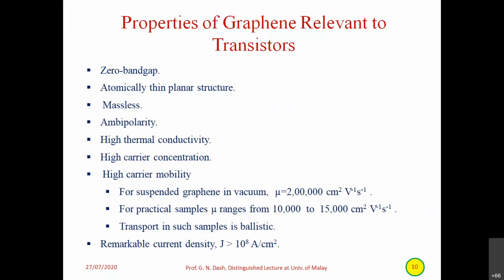For suspended graphene, we have mobility 2 × 10^5 cm² per volt per second. For practical samples, however, the mobility reduces to about 10,000 to 15,000 units. Transport in such samples is ballistic, and therefore the diffusive theory that we are already following may not be applicable, so we have to devise some new ballistic transport. The remarkable current density it can support is more than 10^8 ampere per centimeter square.